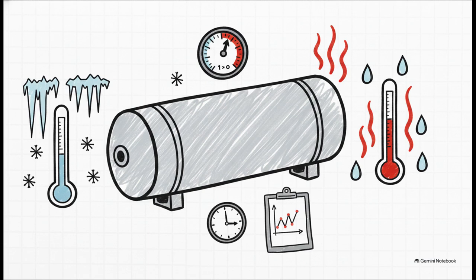Then they swing it completely the other way. The cylinder has to endure high temps of 65 degrees Celsius at 95% humidity, holding that massive pressure for 48 straight hours, just to test environmental fluid exposure.